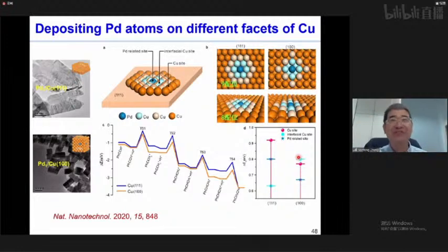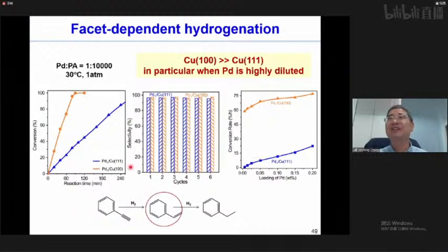Okay, so how can we prove this? What we did is rather simple. As you can see here, after we prepared these two catalysts, we indeed found that the palladium on copper 100 is more active, although they have the same palladium loading amount. In particular, when the palladium is highly diluted, right? If it's highly diluted on Cu(111), it's not active at all. But if it's on 100, it's highly active. So this is quite interesting. It really suggests that our DFT calculation is quite reliable, right?